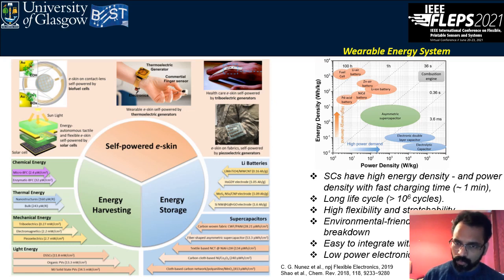But the problem with such batteries is that they generate heat, which may not be good for a wearable application, especially on skin. Also, the charging time for such a battery is more than 1 hour to get a full charge, and some of them are not flexible. Moreover, the life cycle of these batteries is very low, almost 10 raised to 3 cycles.